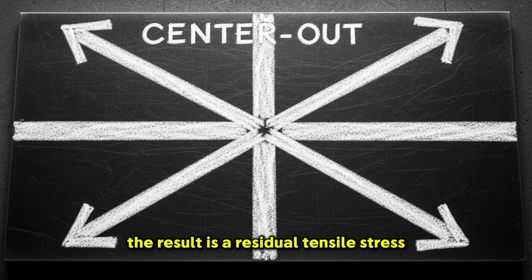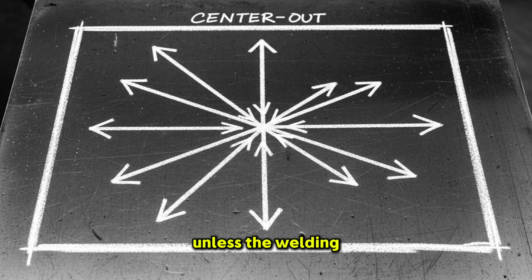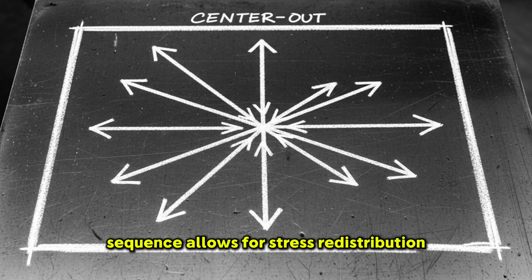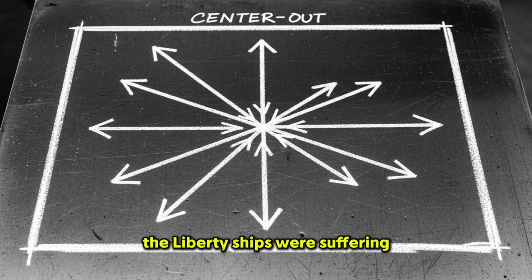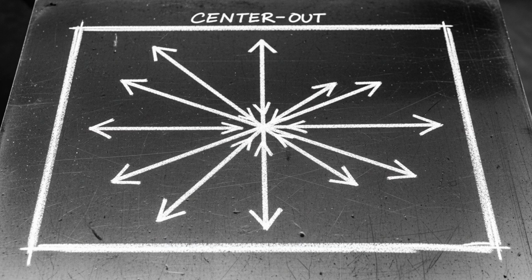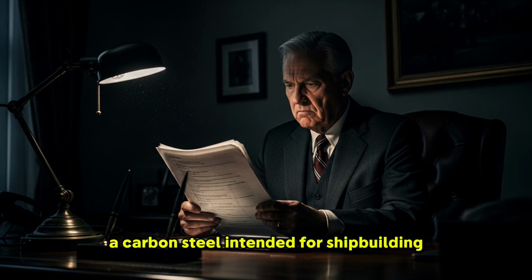The result is a residual tensile stress permanently locked into the structure unless the welding sequence allows for stress redistribution. The Liberty ships were suffering from what metallurgists call brittle fracture propagation. The steel used in their hulls, a carbon steel intended for shipbuilding, performed well in warm waters, but it underwent a critical transformation in the near-freezing temperatures of the North Atlantic. Below a temperature of about 40 degrees Fahrenheit, the steel's ductility collapses.